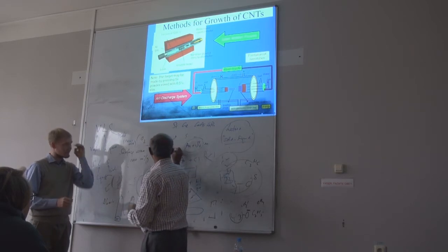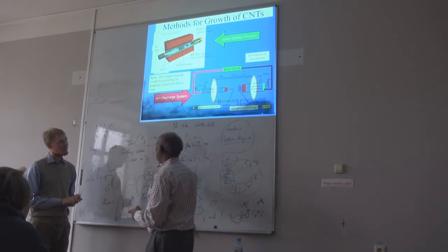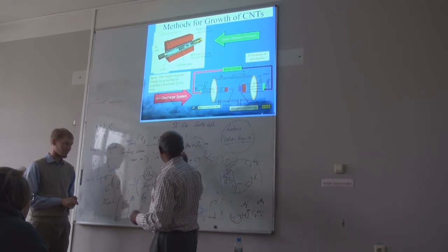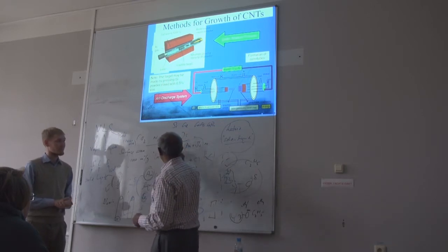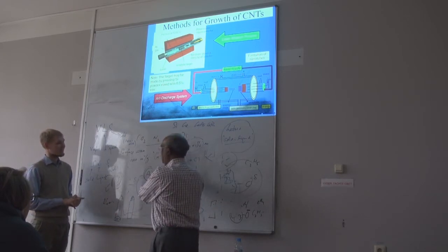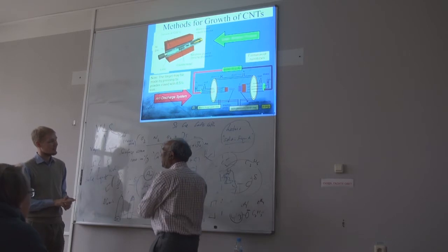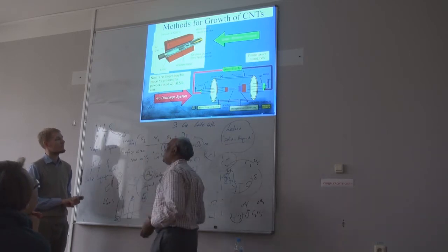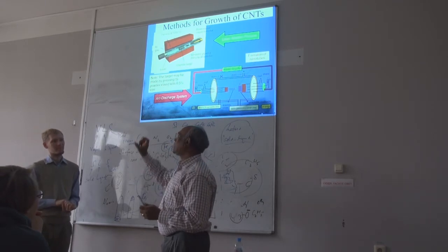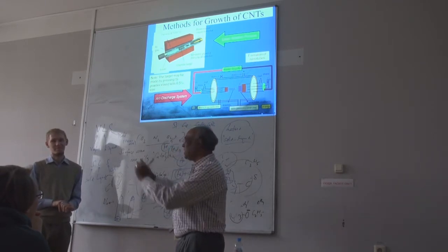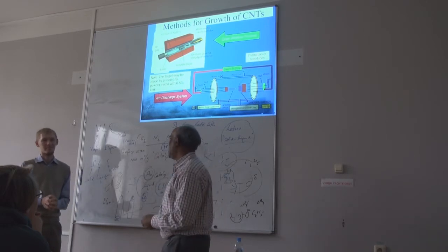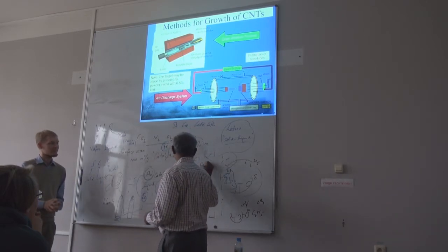Eventually they will make iron carbide. This is a bad catalyst. But if you have water, it will prohibit this carbide formation. That will make it grow longer and become vertical. You can make something called a nanotube forest. It looks like a lot of nanotubes as a forest here. That's called super growth.